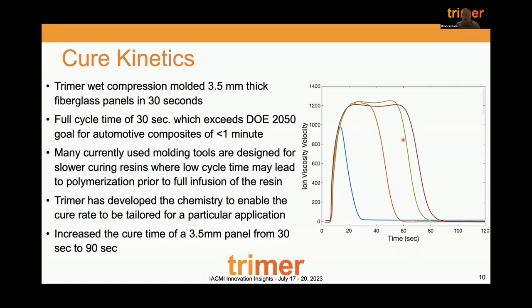What you see in all of the downslopes in all of these is that they're the same. So this material is snap curing at the same rate. And what we do is we just dial in that low viscosity region. How long does it need to stay at a low viscosity before it snap cures? That's a really unique aspect of our material, where we can tailor a solution to a particular part.